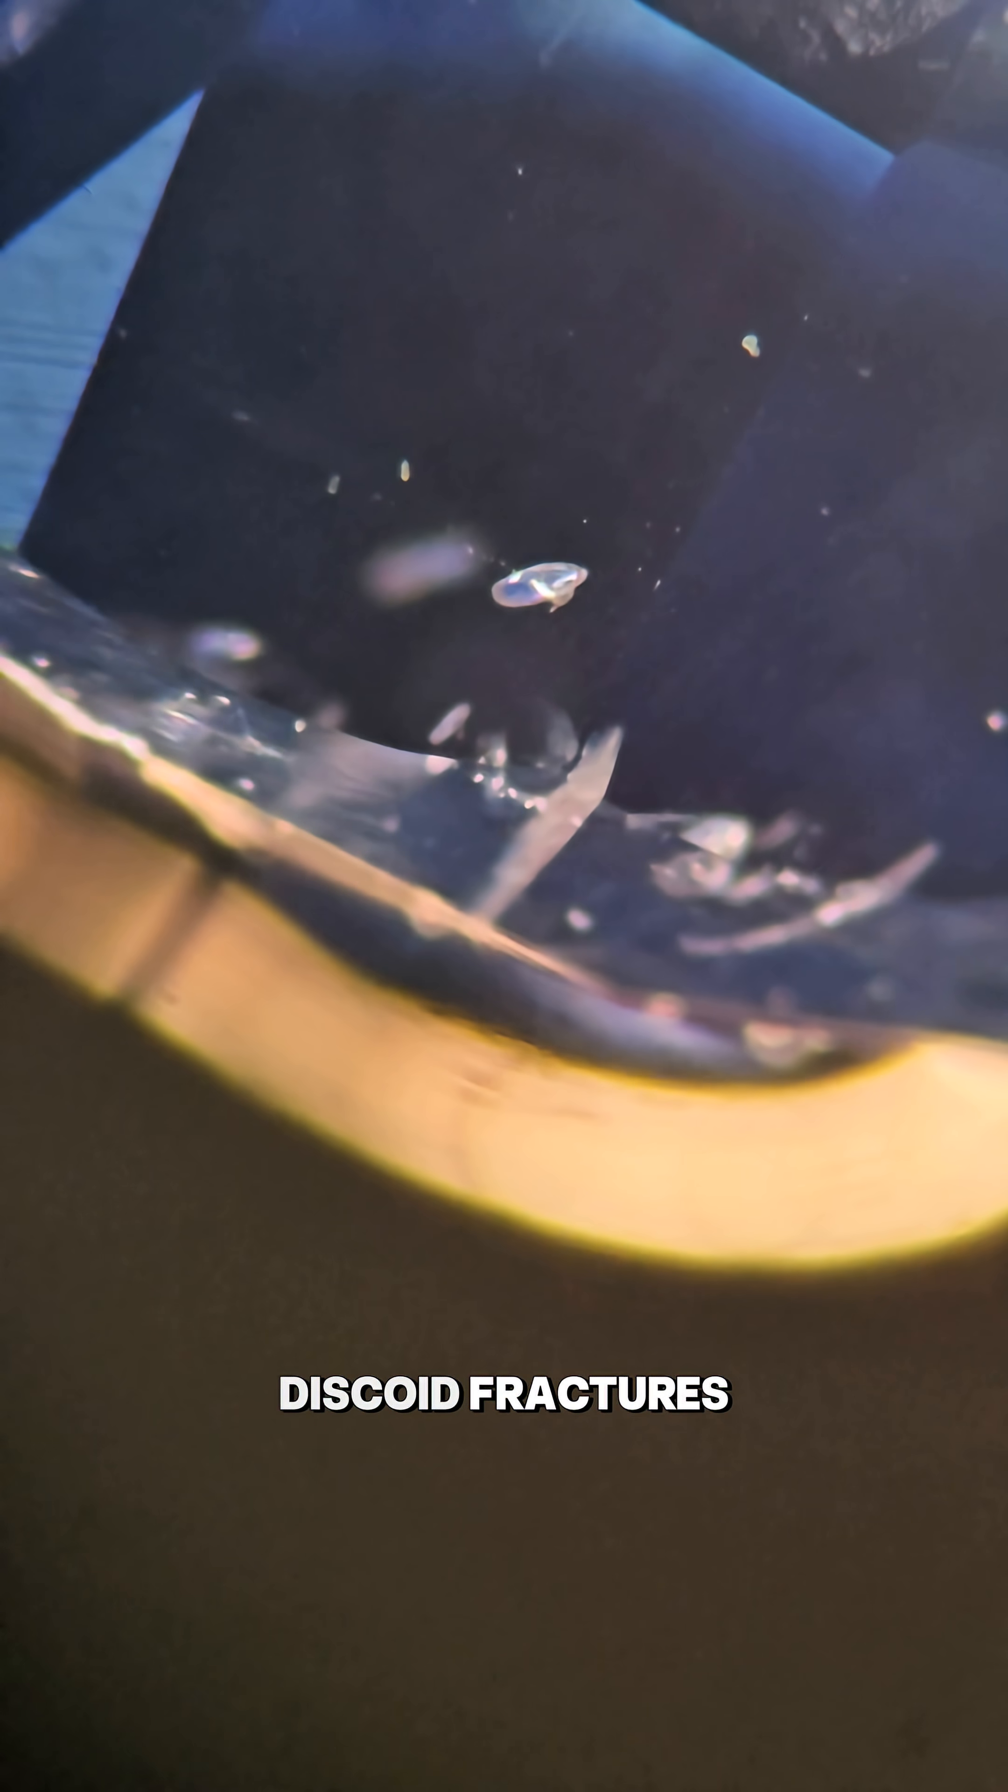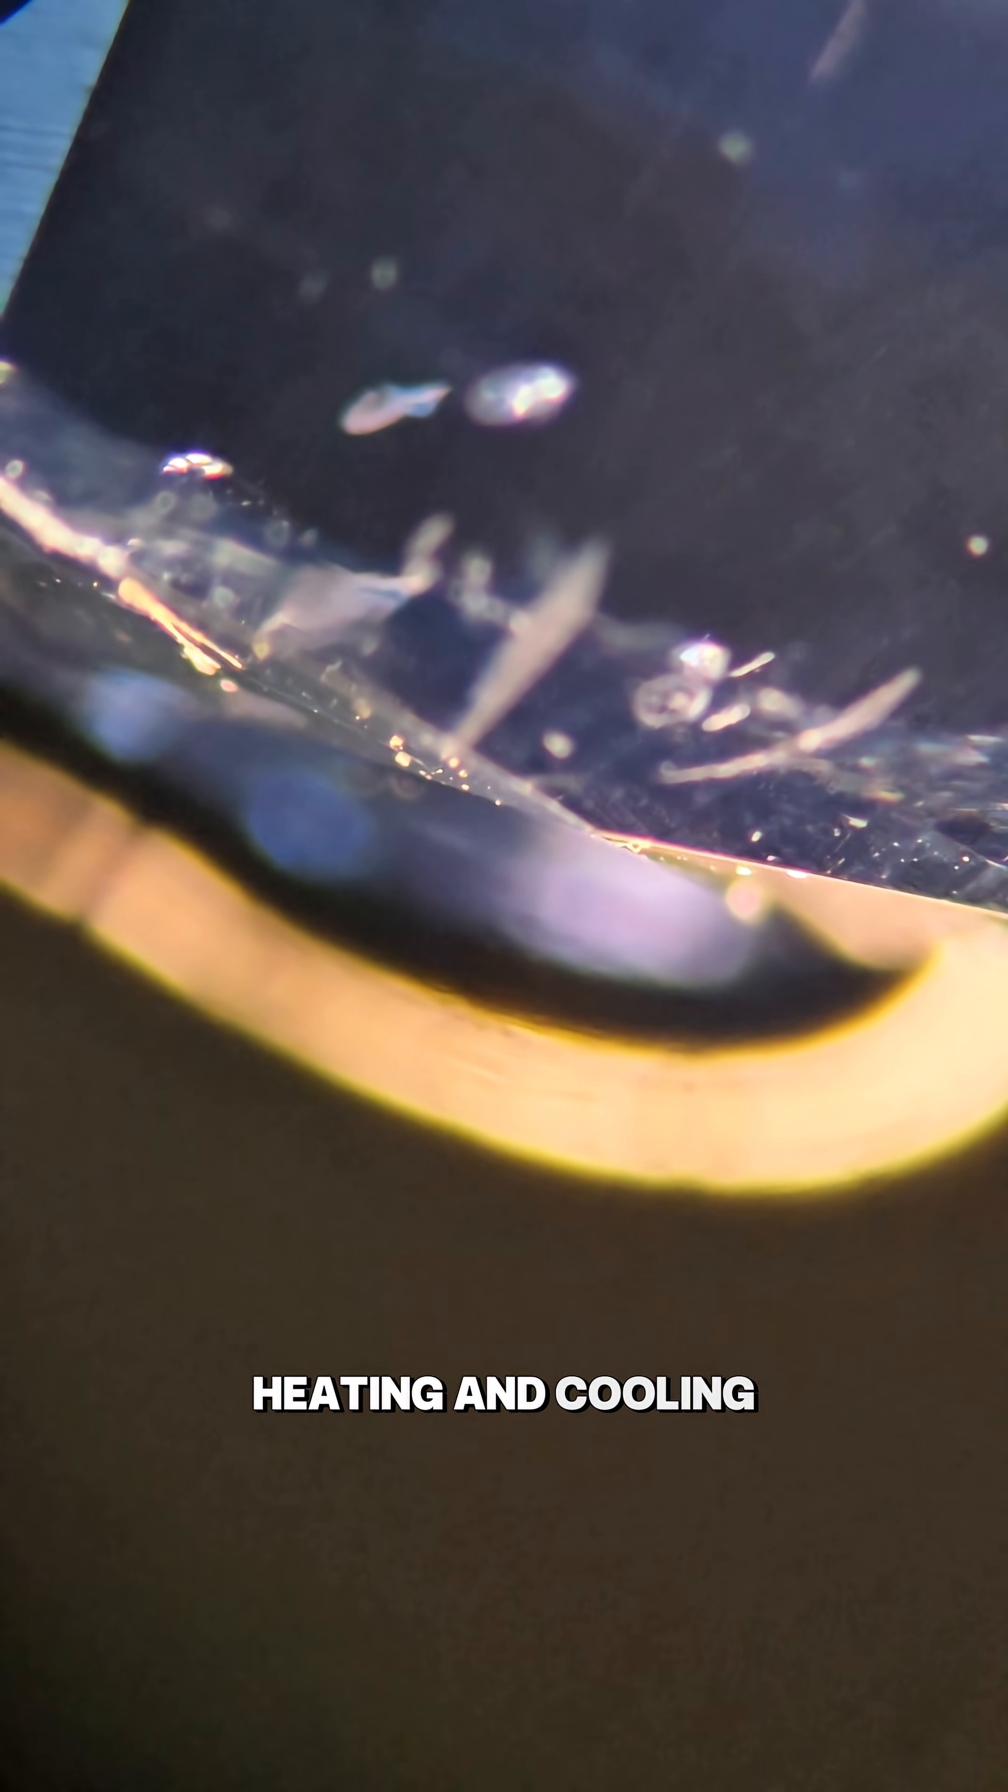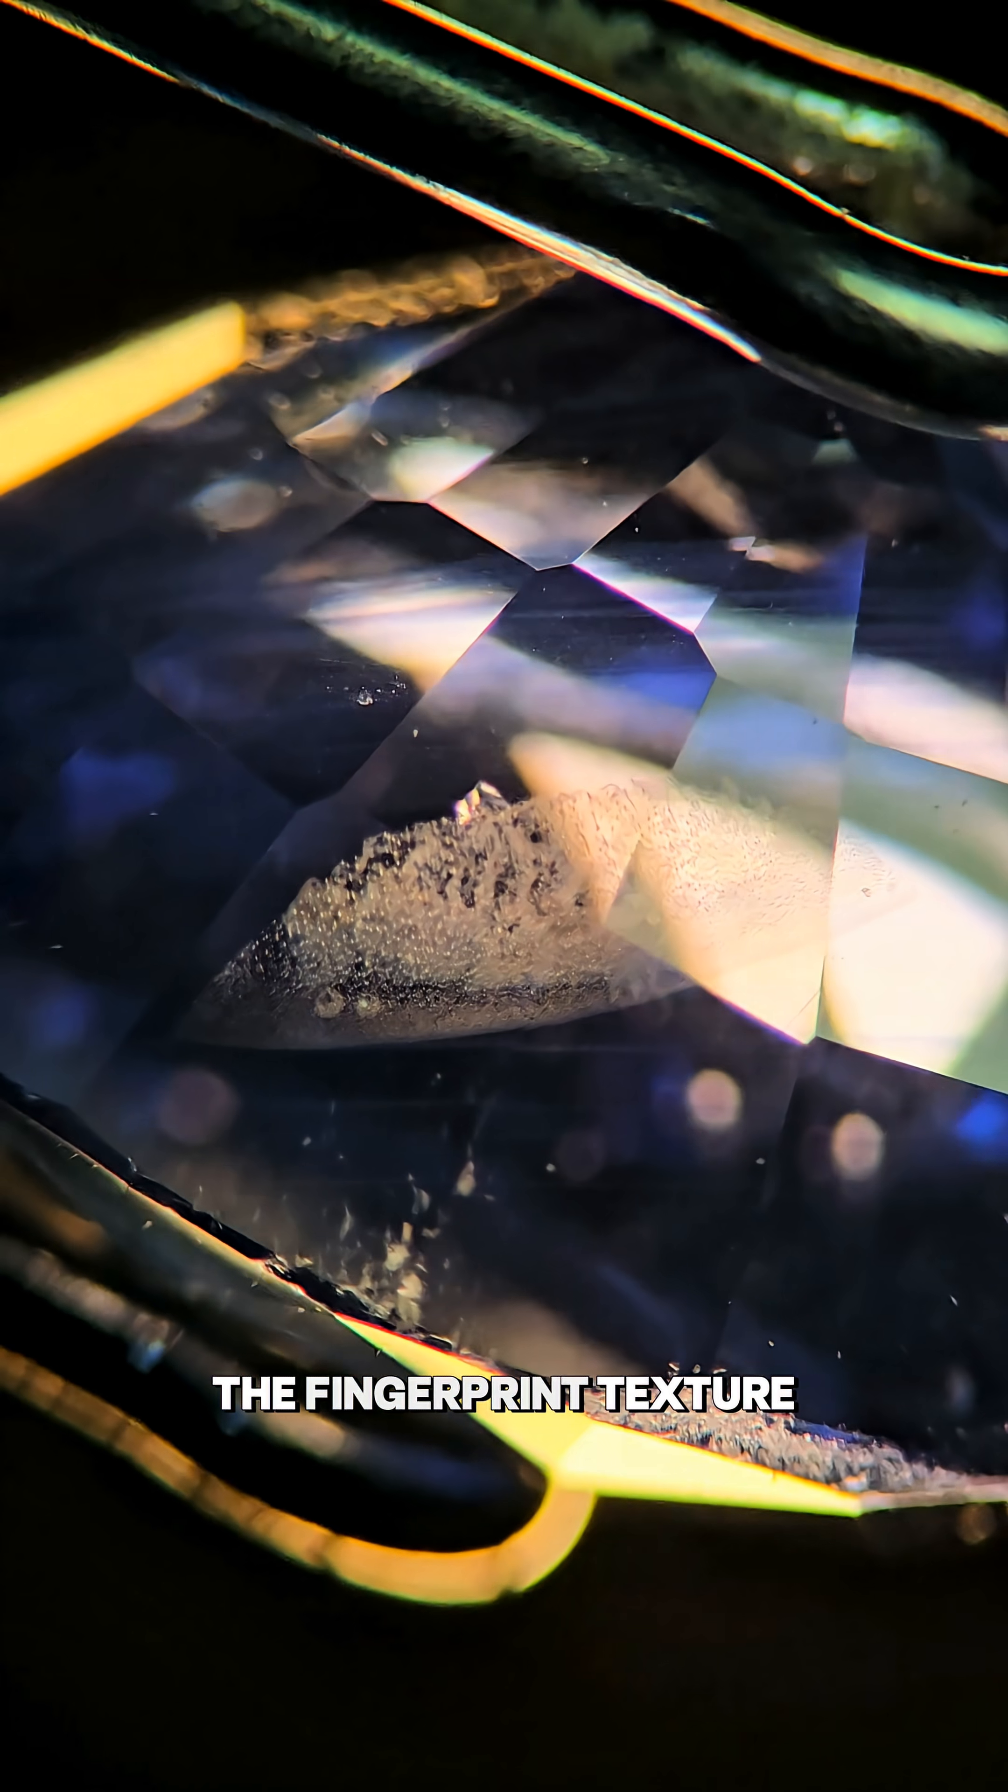And again, more discoid fractures. These are stress fractures caused by rapid heating and cooling. Now when I zoom in on the fingerprint inclusion, look at the texture—it's melted. There's a whitish cloud to it. The fingerprint texture has been changed.